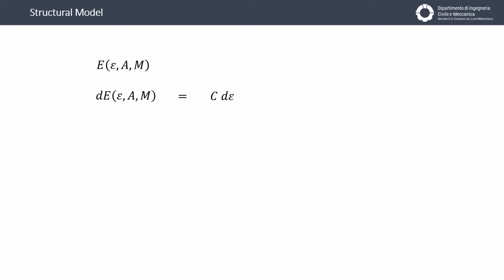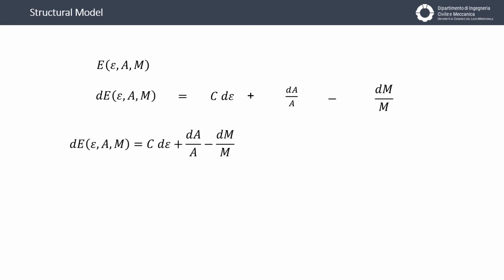In this case, the model is perfectly linear. It's the model that we can see in literature. But in this case, we use the contribution of the austenite, the variation of austenite on the quantity of the austenite, plus the contribution of the martensite in the same manner, but using a negative sign, because we postulated that the austenite transforms in martensite and vice versa without any other phases, intermediate phase.